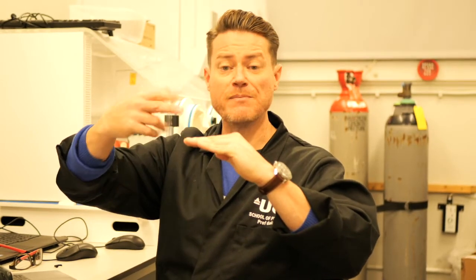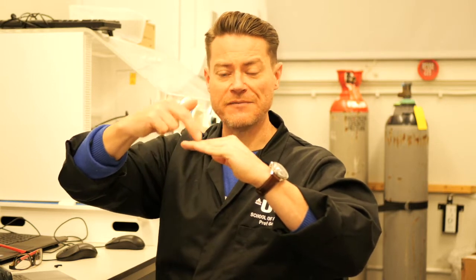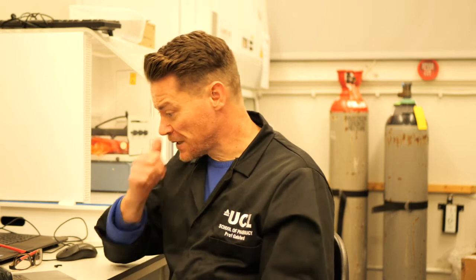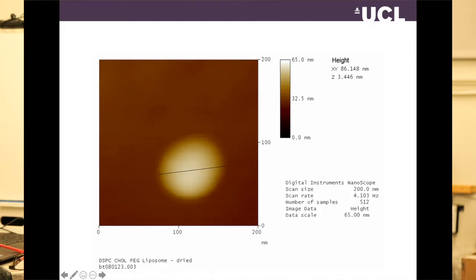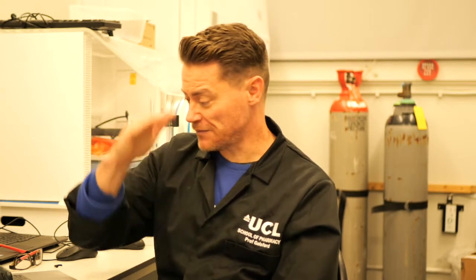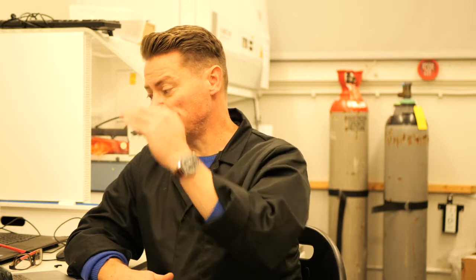And then what you can do is you can, again, move the tip over the surface of the sample and measure the thermal conductivity of your sample at various points. And in that way you can build up a topographical image on thermal conductivity, not just on Z position. Okay? So the example in front of you is a single liposome in water, and it's being imaged. And so in this instance you've got height, Z, on the box. So the height above the baseline for the AFM is being colour-coded. Dark brown means it's at the baseline, and it goes all the way up to white, which in this case is a height of 65 nanometers, 65 nanometers, that's very small.